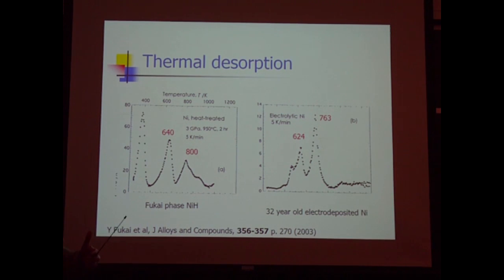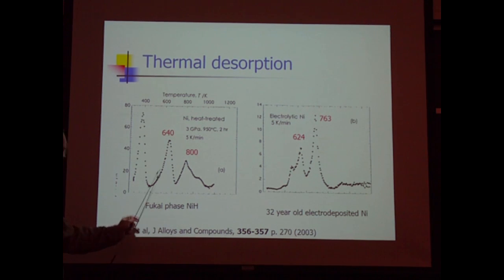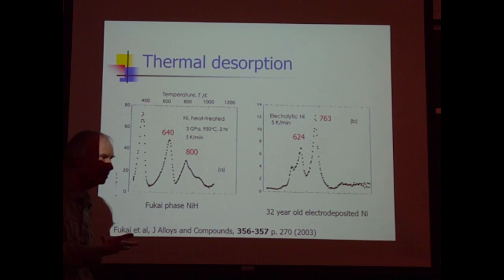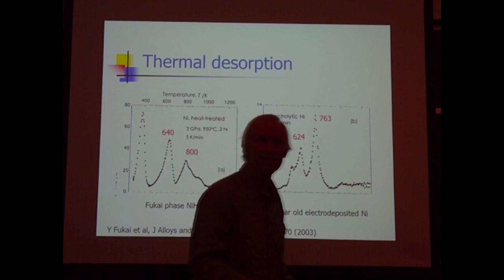On the other hand, if you crank up the current density, if you really get high loading and you've stabilized the vacancies, and you co-deposit under conditions where you stabilize the vacancy, you should be making lots of them. You should be making Fukai phase material, which means if you do thermal desorption, you should get peaks like this show up. Also, if you only make a few vacancies, these peaks will show up, but they'll be small. If you make a lot of vacancies, these peaks will show up and be much larger. So you have the possibility now of having a diagnostic that will be able to actually prove that you've made the vacancies through this method. So far, no such diagnostic has been implemented.